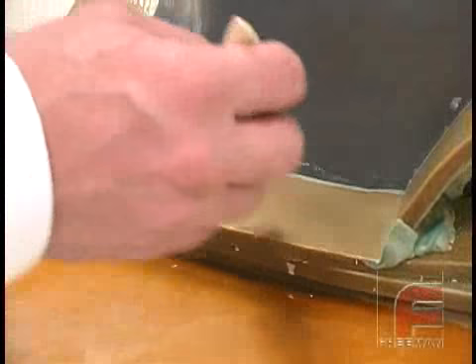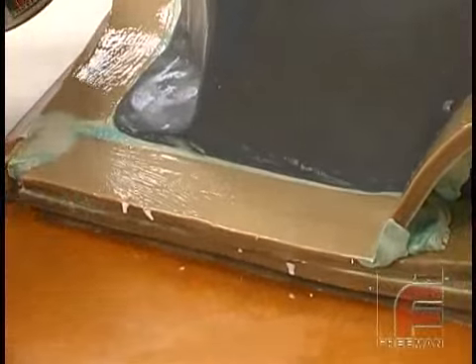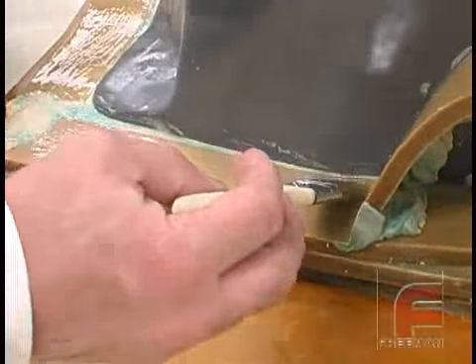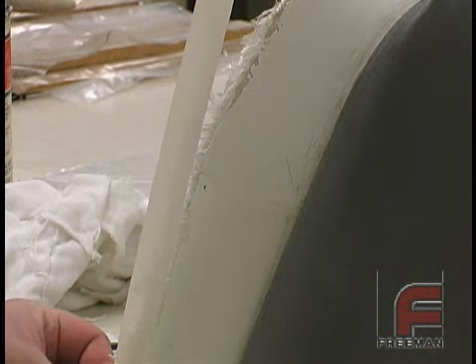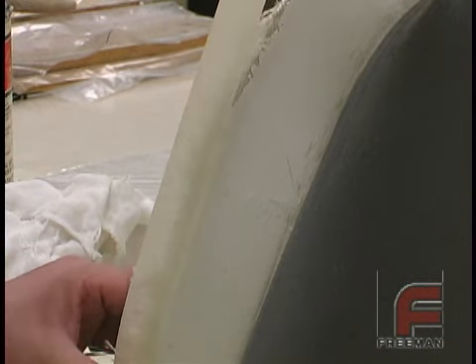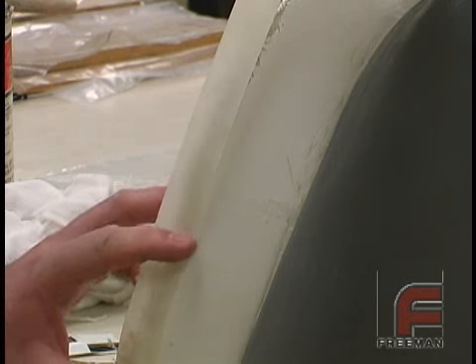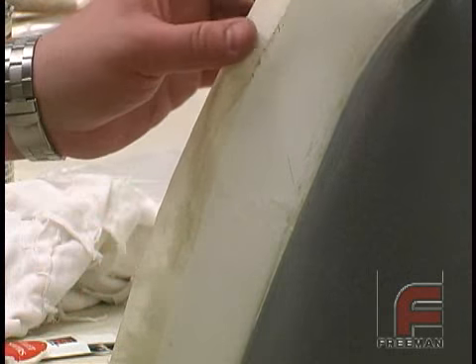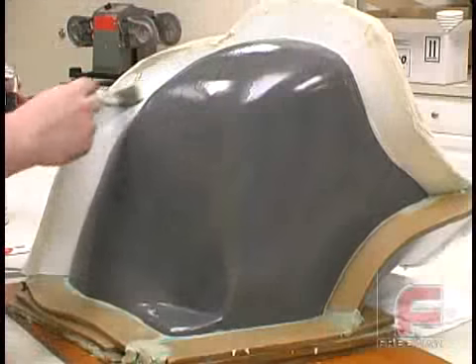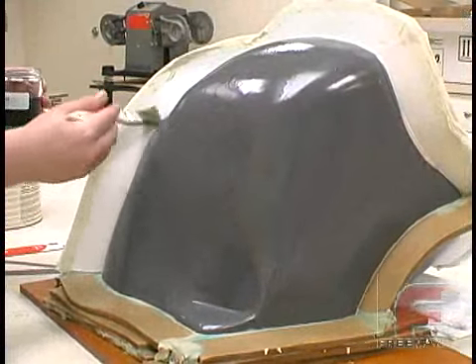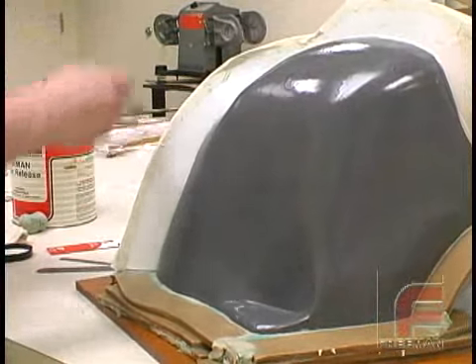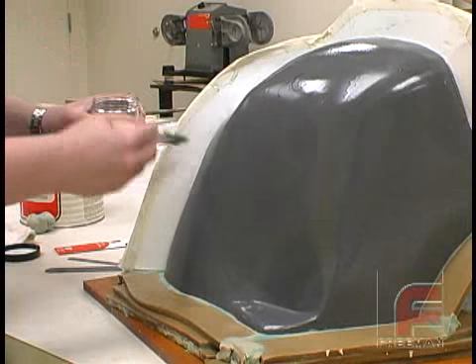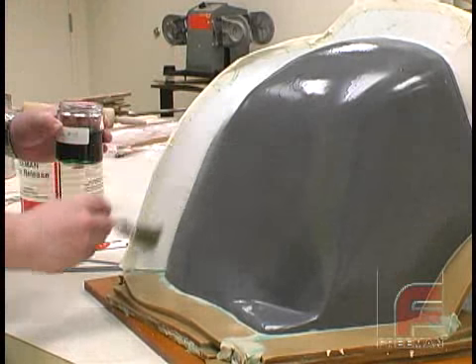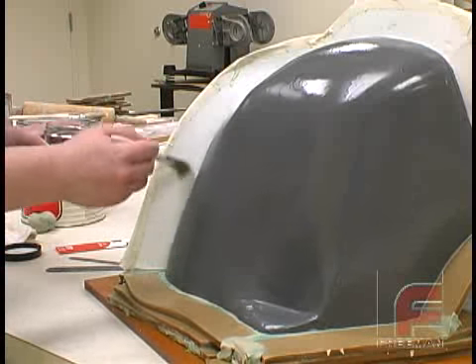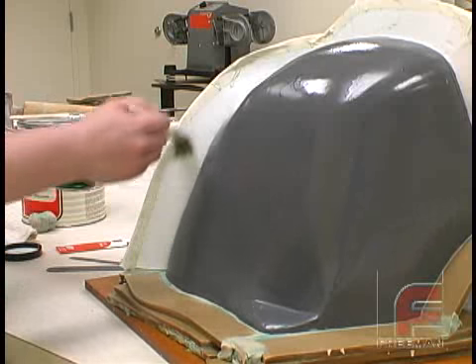After applying the wood and plaster sealer to the sheet wax, we cover the ends of the first part of our mold with masking tape. This is done to prevent any of the new material from accidentally seeping into the edges of the first part and therefore locking the two parts together. Finally, we apply our two coats of wax release, two coats of PVA, and our last layer of wax release. Our wax release will also dissolve some of the excess clay that we hadn't removed earlier.